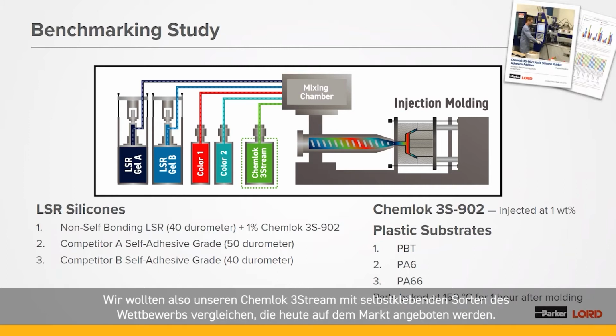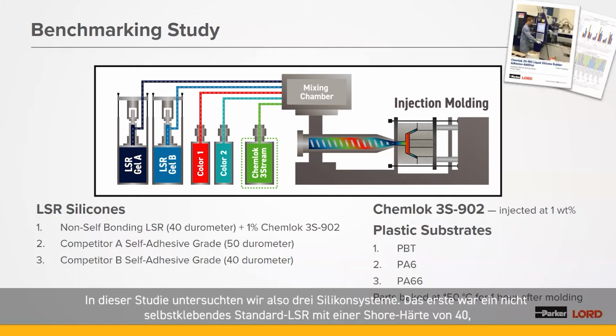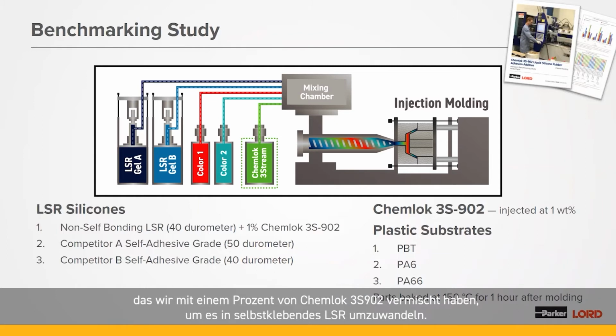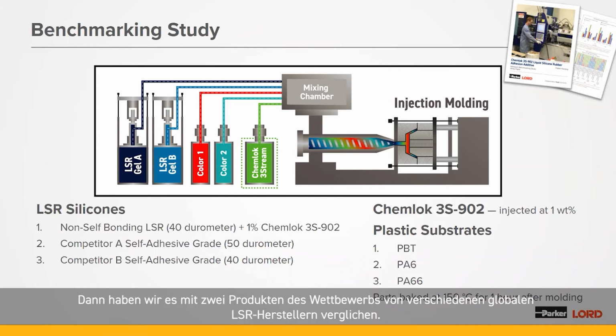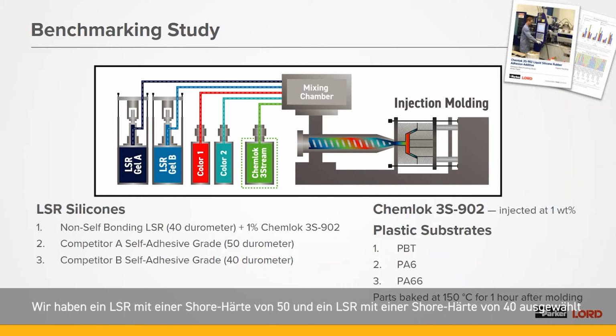So what we wanted to do here was take our Chemlok 3-Stream and compare it to competitive self-adhesive grades that are on the market today. So in this study, we took three silicone systems. The first one was a 40 durometer standard non-self-bonding LSR, and we added 1% of the Chemlok 3S902 to that to convert it to self-bonding. And then we compared that to two competitive products from different global manufacturers of LSR. We picked a 50 durometer grade and a 40 durometer grade.